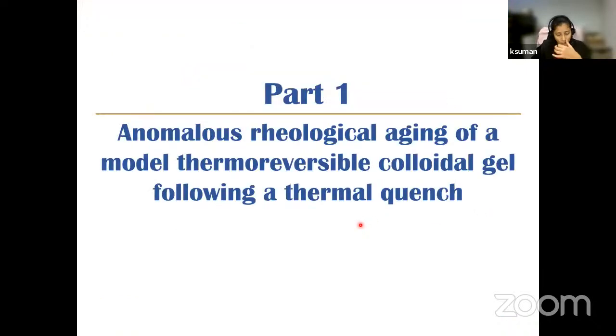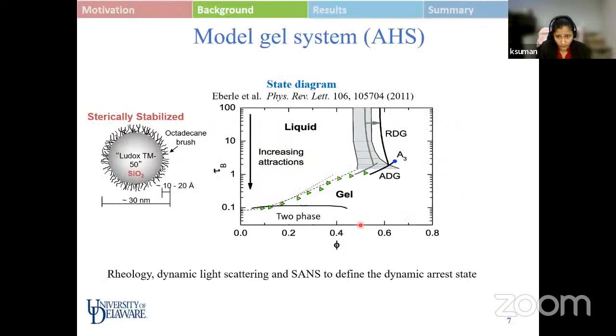So with this brief overview, we move to the first part of the talk, which is going to focus on anomalous rheological aging behavior of a model thermoreversible colloidal gel following a thermal quench. As I stated, the first step is the selection of a good system. The system here is the adhesive hard sphere system, abbreviated as AHS. This is a model gel-forming thermoreversible system, which has been very well characterized in the literature. These are 30 nanometer particles of silica coated with octadecane, and it is known to undergo a liquid to soft gel transition on decreasing the temperature.